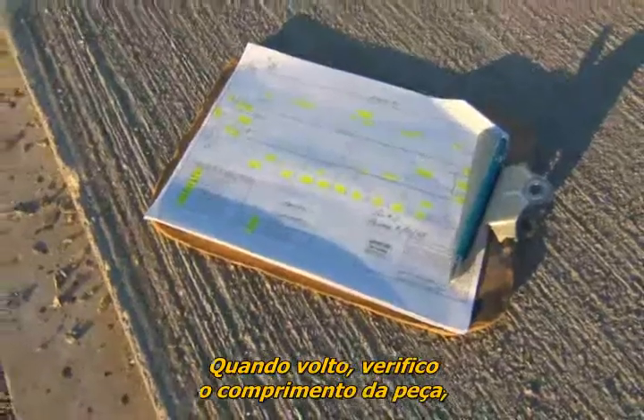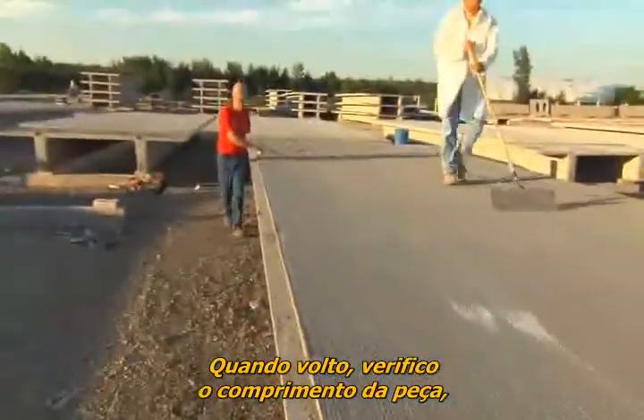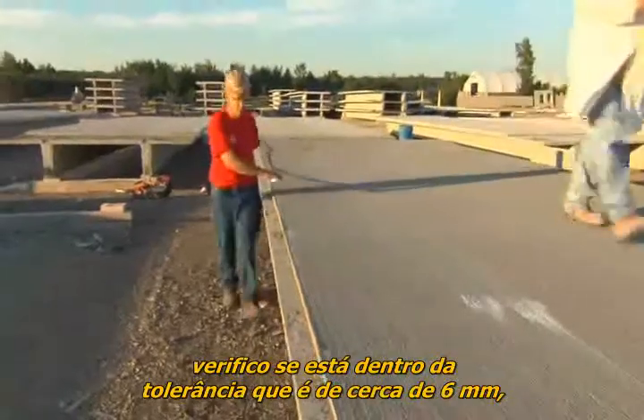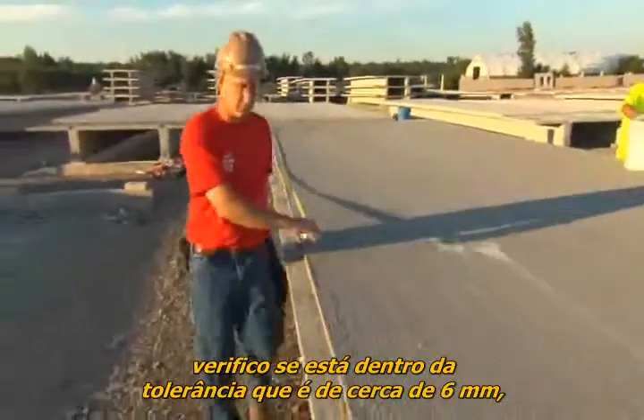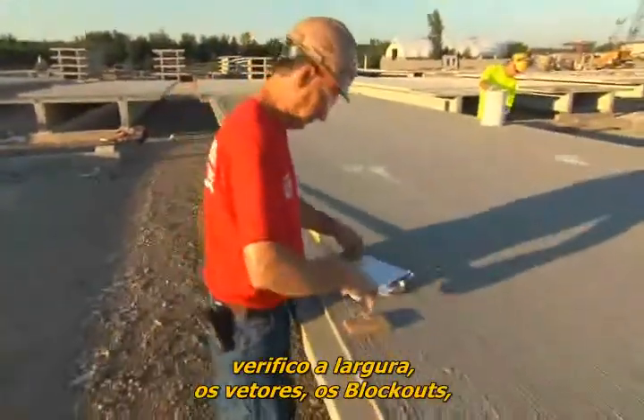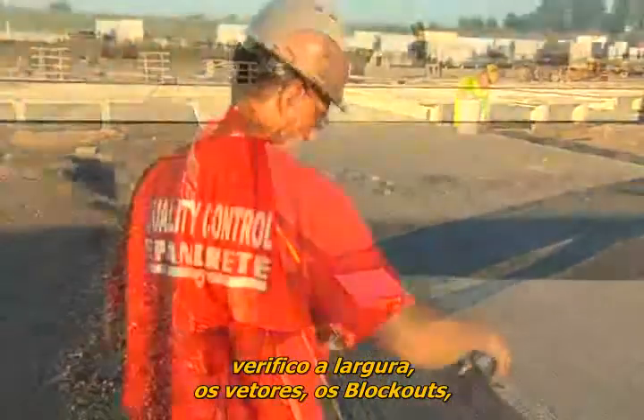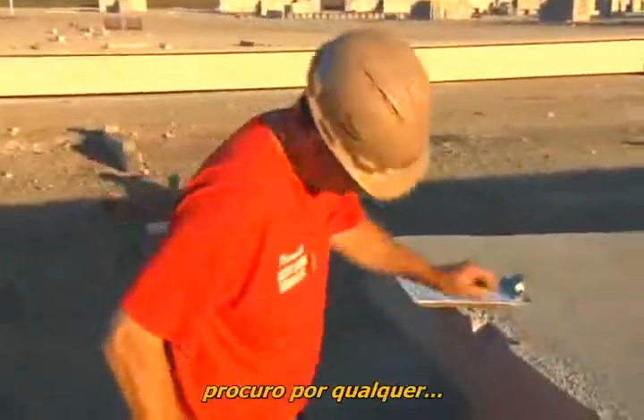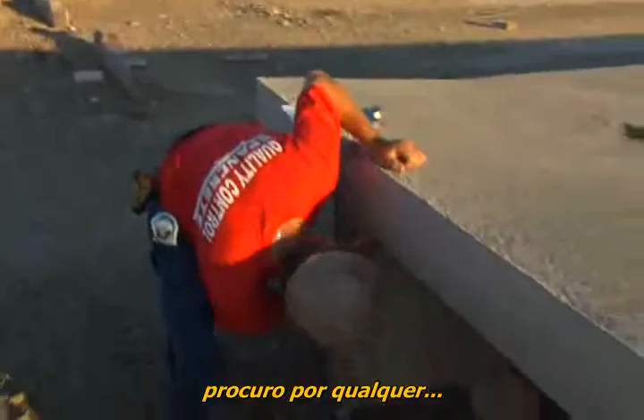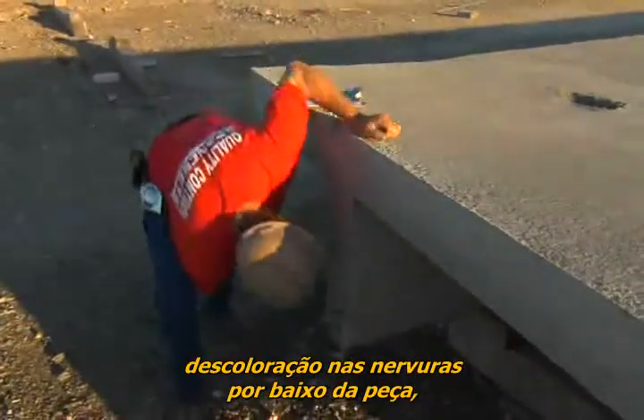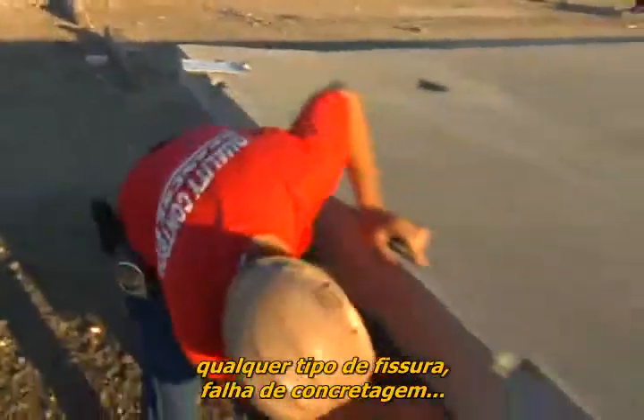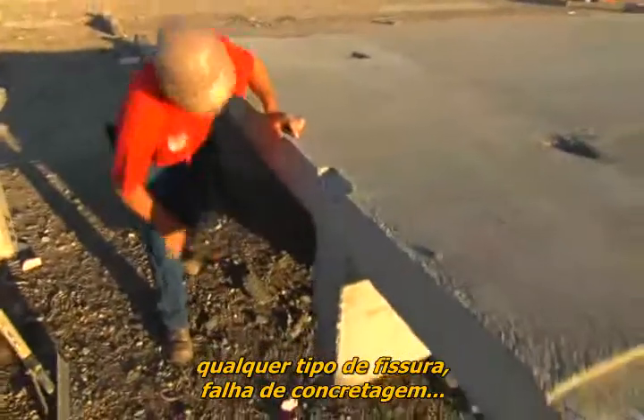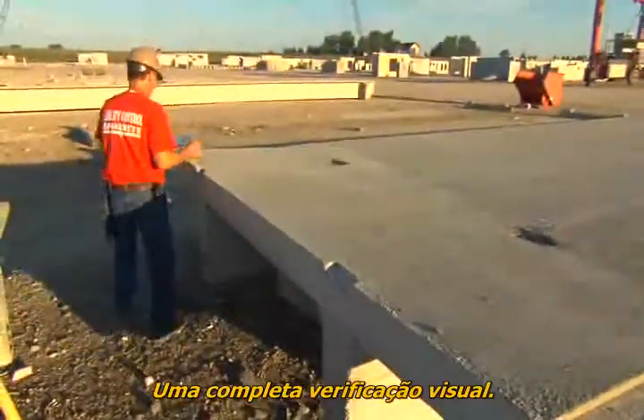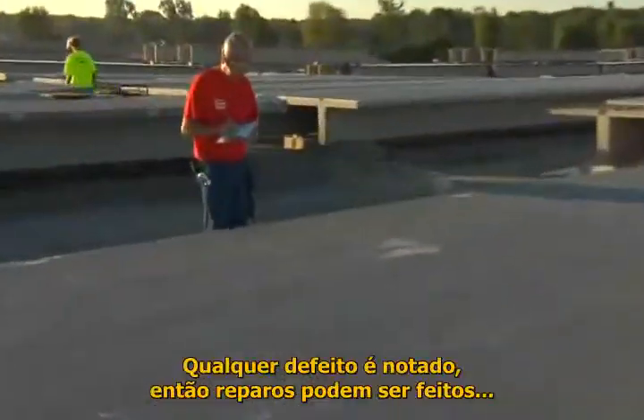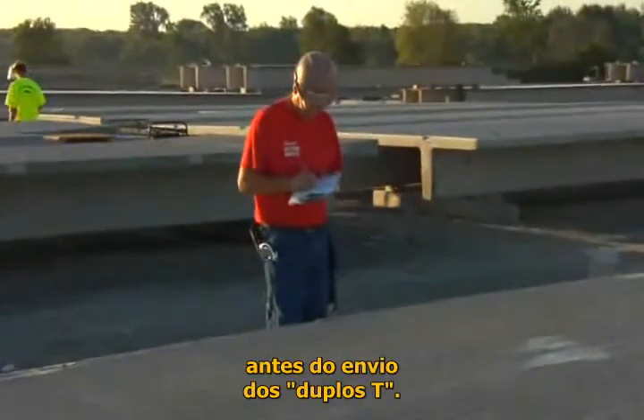When I first get back there, I go and check the length of the piece and verify that within a tolerance of probably a 1/4 inch or so. Check the width, we check the vectors, we check the electrical blockouts. I do a visual for any type of discoloration in the stems underneath the piece, any type of surface cracks, bug holes, just do a complete visual. Any defects are noted so that repairs can be done before shipping the tee.